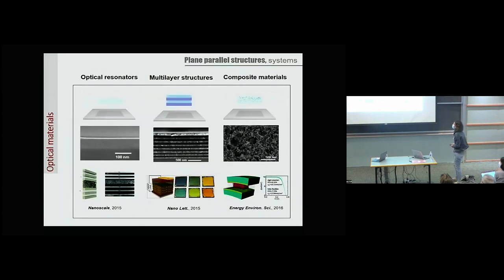As I told you before, we had some experience growing optical resonators, multilayer structures, or composite materials. So we could, for instance, include luminescent species in a mesoporous film in between two mirrors, and by modifying the local density of states, you can modify the optical properties of your system. We could also endow perovskite solar cells with colors by including one-dimensional crystals, or we included disorder in dye-sensitized solar cells, and we could have a record-efficiency flexible solar cell.